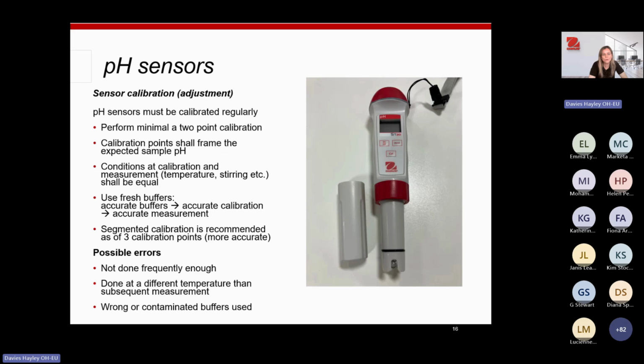Sensor calibrations. Your pH sensors must be calibrated regularly. It is always advised to do a minimum of 2-point calibration, and when we say 2-point calibration, we mean at 2 different pH levels. So you can do it at pH 4 or pH 10. It's generally advised, if you know the expected pH of the solutions you're going to be sampling, to do your pH points either side. So if you're measuring something of pH 7 in value, you can calibrate it at pH 4 and pH 10, just to encompass the expected pH of the sample.